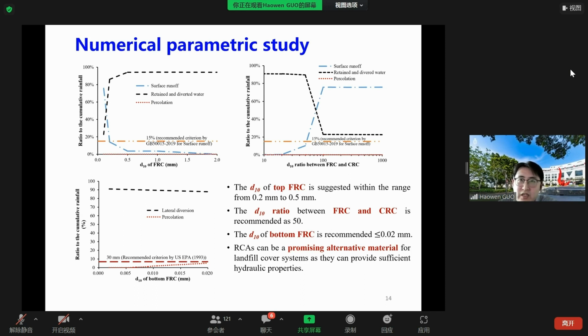As shown in the figure, the surface runoff reduced to less than 15% when D10 of FRC is larger than 0.2 millimeter. This meets the recommended criteria by the national standard for the surface runoff of greenland. However, the D10 of FRC does not influence the retained and diverted water when the FRC D10 is larger than 0.5 millimeter. So the D10 of the top FRC layer is suggested within the range of 0.2 millimeter to 0.5 millimeter.